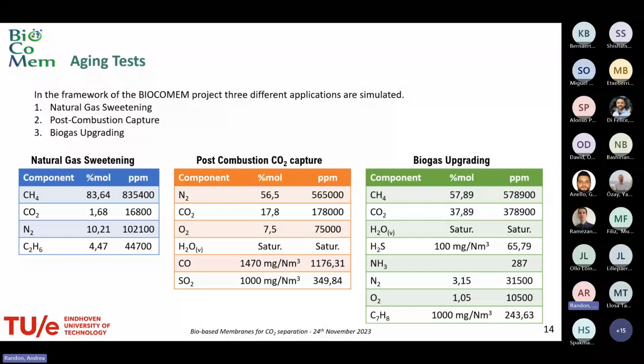So there are 3 different applications in the Biocomem. These are the composition that we chose for the aging test. For the 3 different applications, the first one, natural gas, we chose ethane as representative of the hydrocarbons. There is a composition also for the post-combustion CO2 capture, in which the pollutants are SO2 and carbon monoxide, and it will be saturated around the 20% of molar fraction of water vapor.